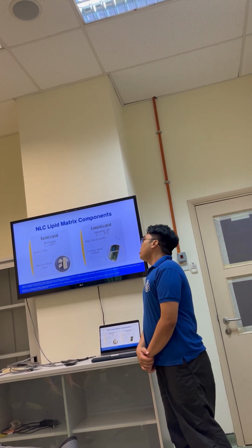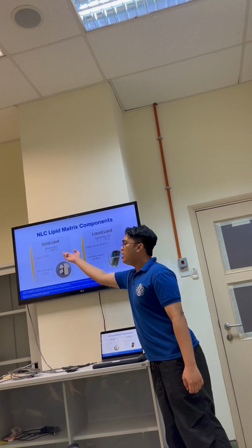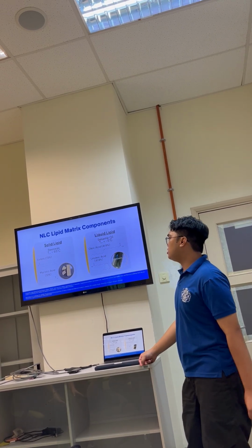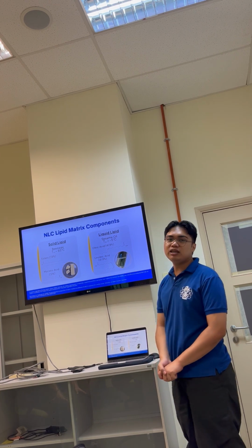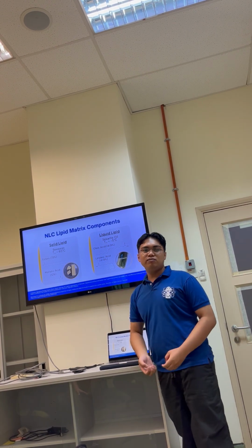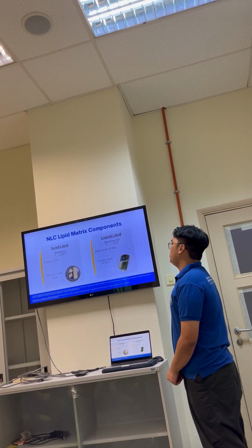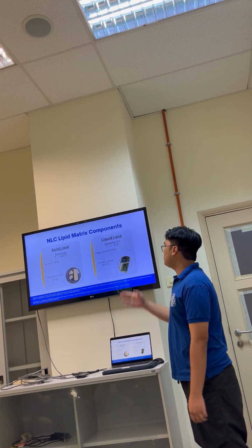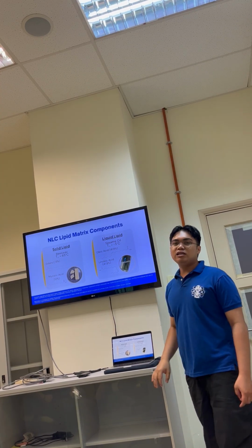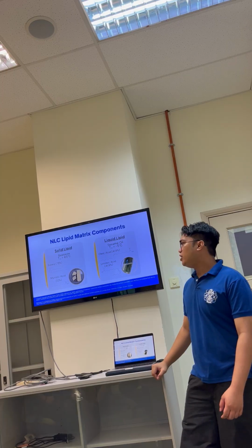Anyway, moving on. The solid lipid can be composed of beeswax because this has a high melting temperature of 65 degrees Celsius. As you can see, the structures are predominantly esters and myristic acid, a free fatty acid form, which they can stack easily on each other. Next is the liquid lipid component. Sesame oil is a safe component that we can use for liquid lipid. It has a low melting point, as you can see, rationalized by the double bond kinks that we have there.